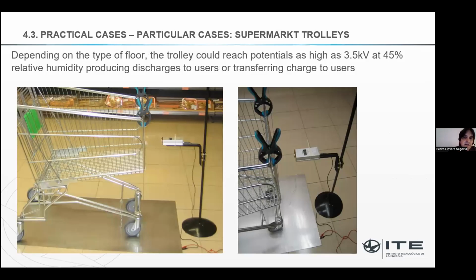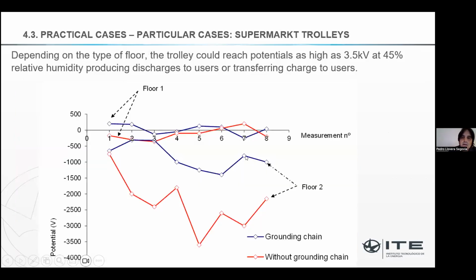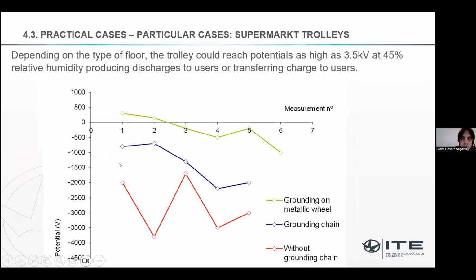It was quite funny. With this new floor, trolleys get charged. They put a chain on the trolley to ground it, but with this grounding just hanging from the metallic structure, it was not very effective because the metallic surface was covered with an invisible insulating surface, and if you connect this grounding chain to a metallic part, then it works. So sometimes you have to be careful how you ground these metallic structures.